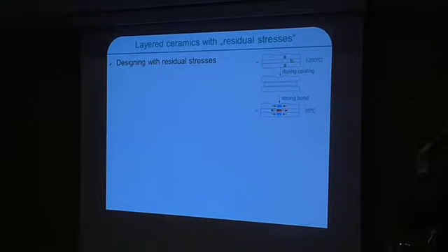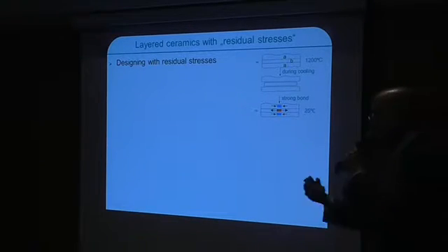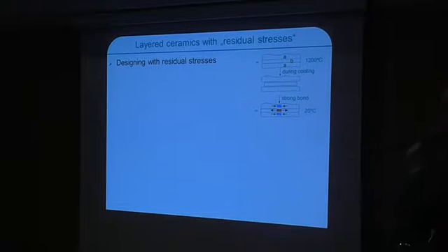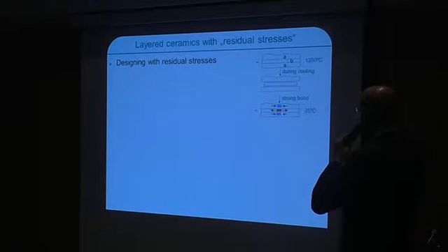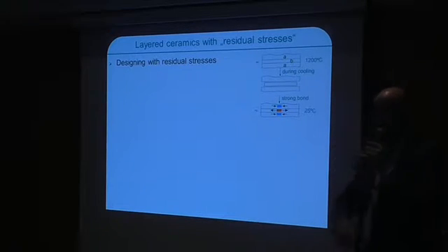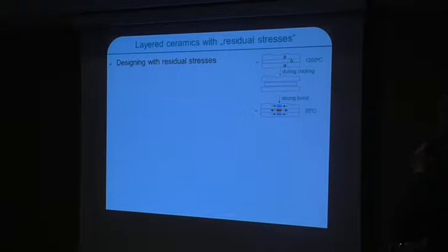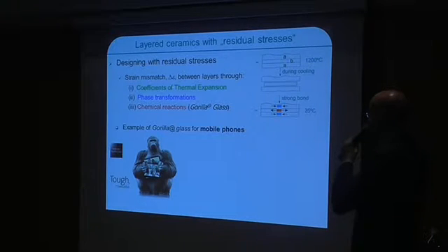And if you are able to ensure a strong interface between the layers, you will get some differential strain, which gives you elastic strains in the layers, and that transforms into residual stresses. Unfortunately, you do not only have compressive stresses, which would be good against propagation, you could also have tensile stresses.